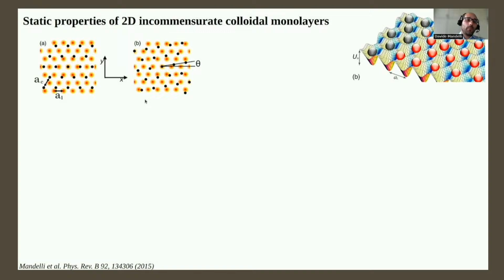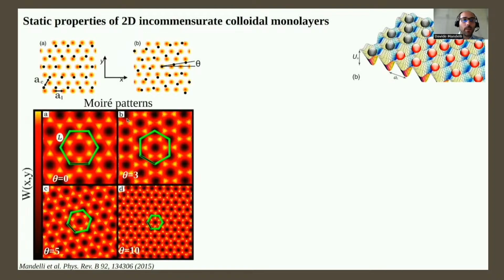Now, when compared to the one-dimensional case, of course, we have additional degrees of freedom, and in particular, it is not known a priori which angular alignment corresponds to the state of lowest energy. The best way of visualizing the effect of misalignment angles between the colloidal crystal and the substrate is by looking at the Moiré pattern, which is shown here for different values of the misalignment angle theta.